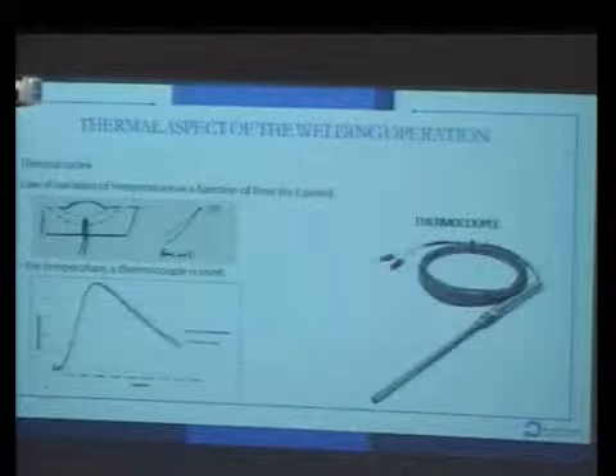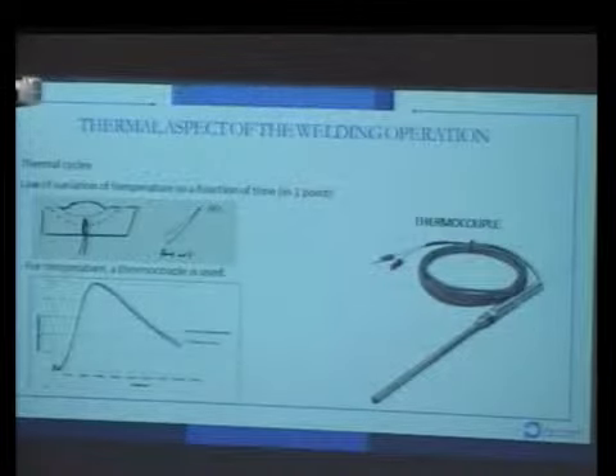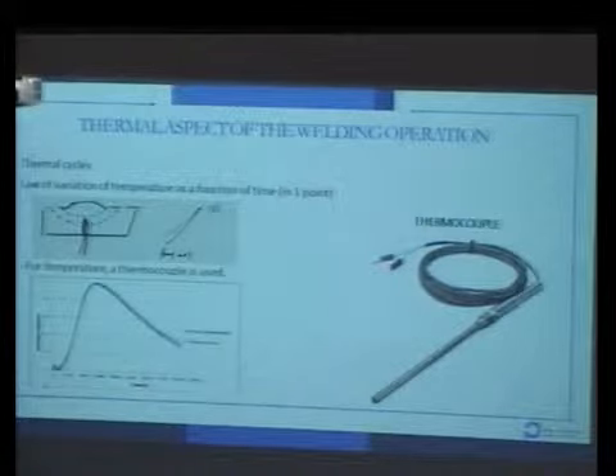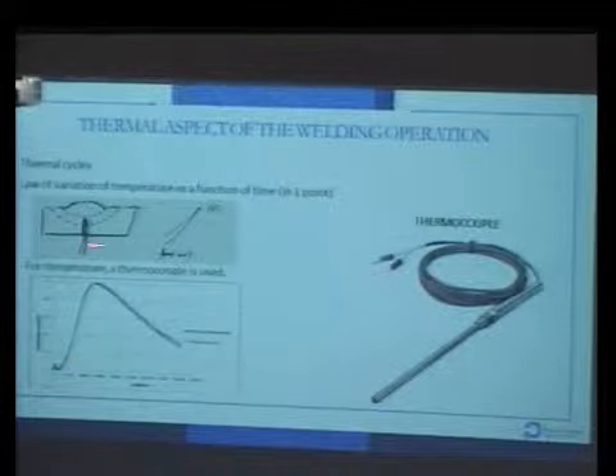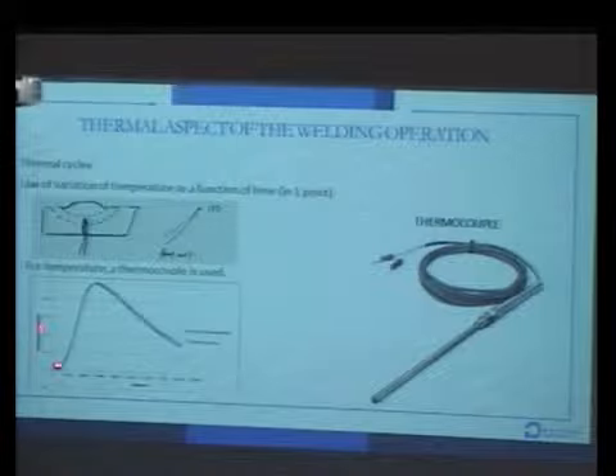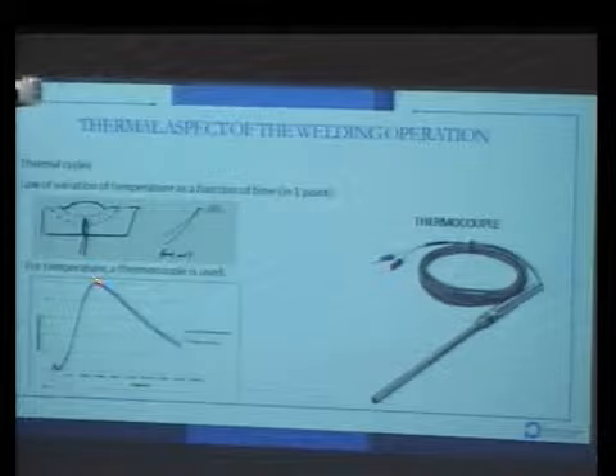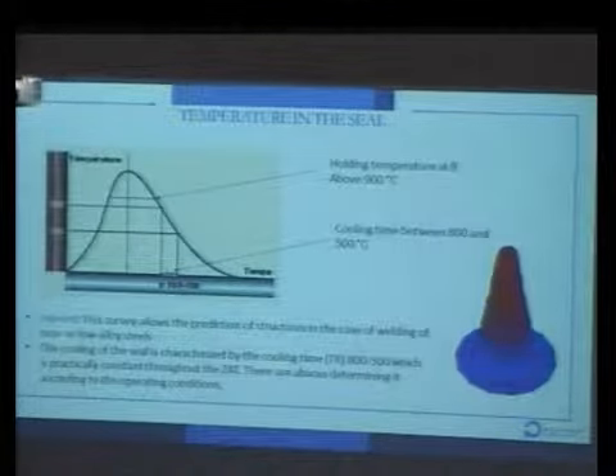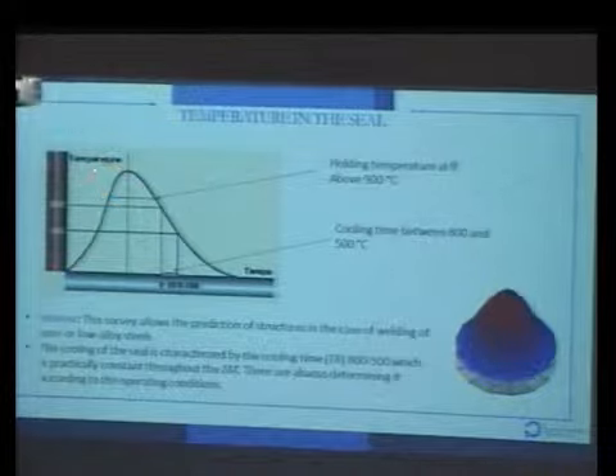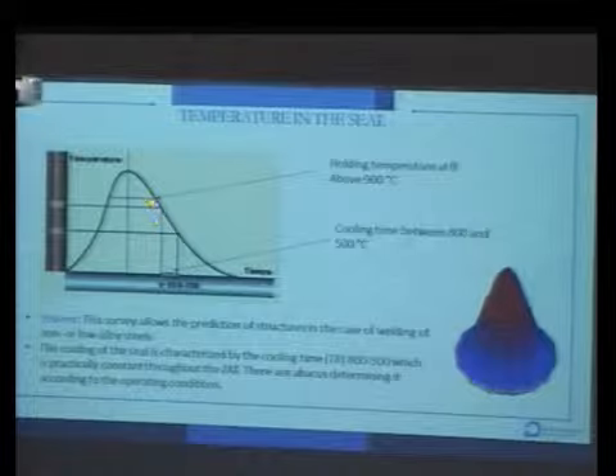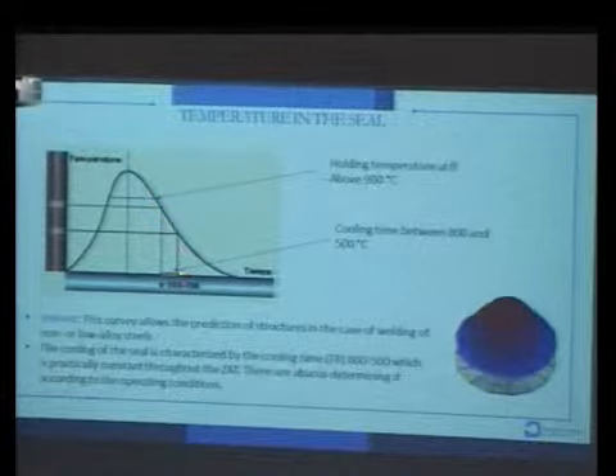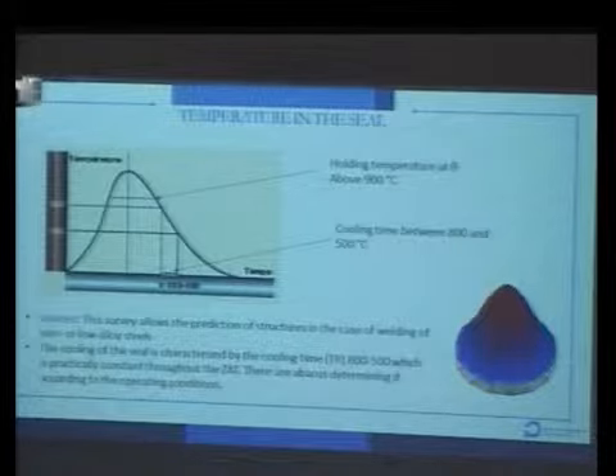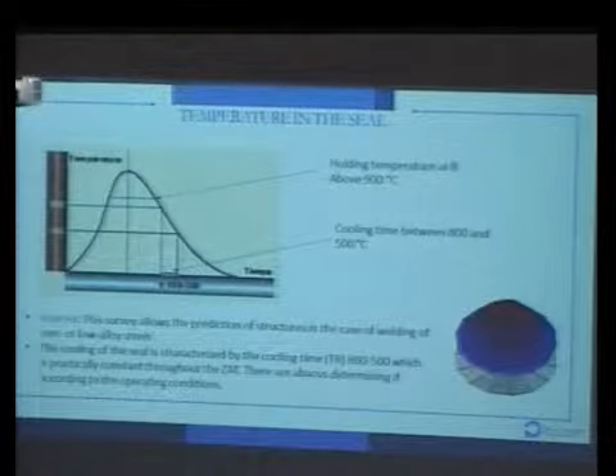And second point, the thermal aspect of the welding operation. When you weld, if you take a thermocouple, you can measure the temperature. When you weld at a point, the temperature grows up and then falls down. Here, you grow up here, here, by definition, higher than the melting point. So here, the time around 800 degrees will be very important, because if this time is very short, you have a risk of martensite. If the time is long, you don't have this risk.